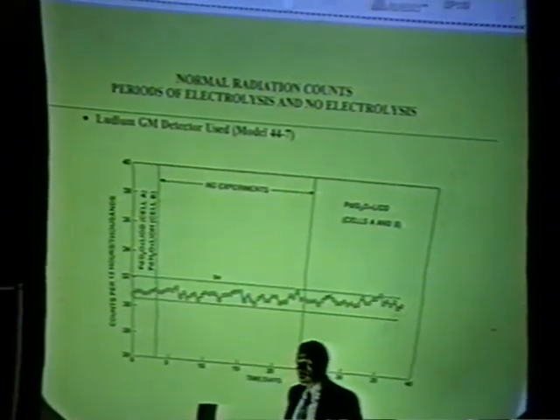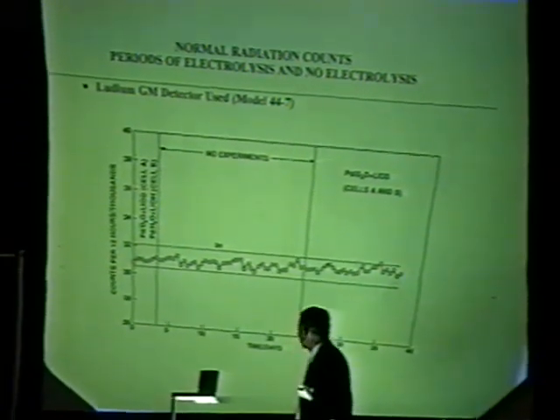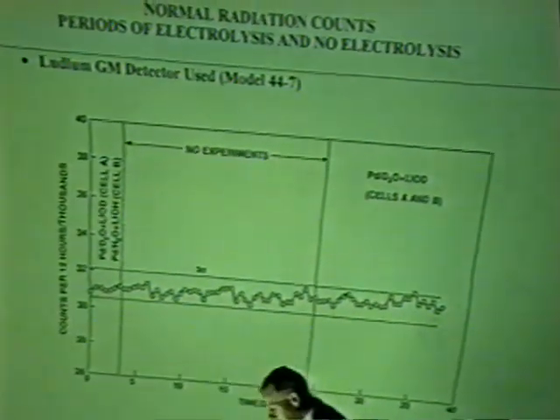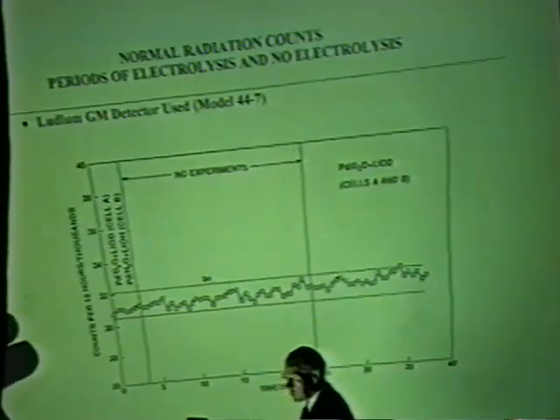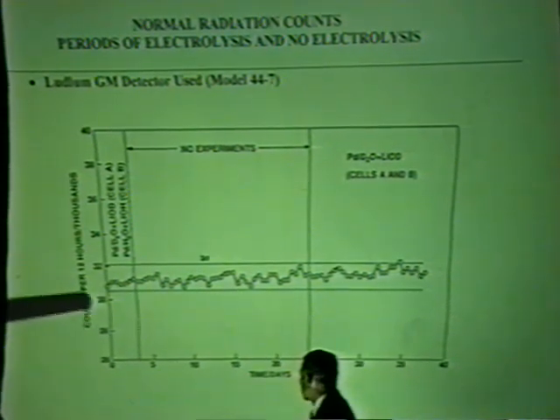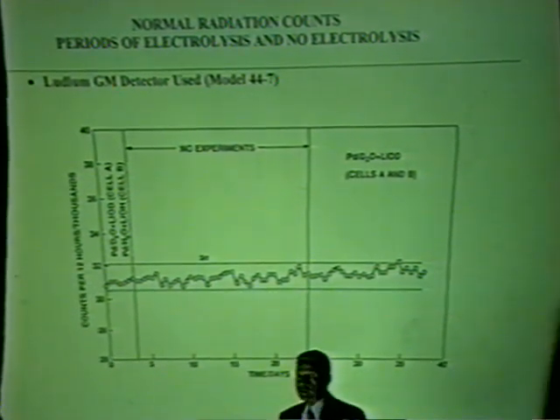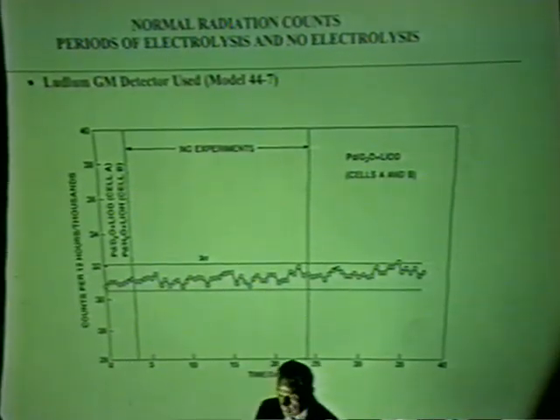Due to safety concerns, we had a Geiger-Müller counter in the experiments to measure radiation. Under normal conditions, month after month, it was often within plus or minus 3 sigma, around 32,000 counts per every 12 hours. That was the usual situation. But in some cases, we saw things abnormal,